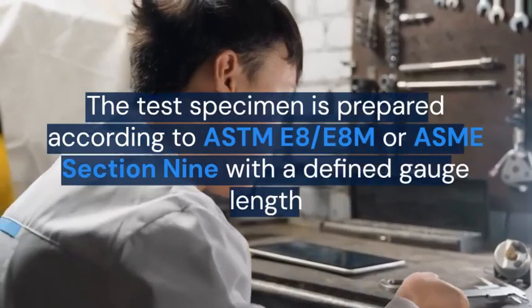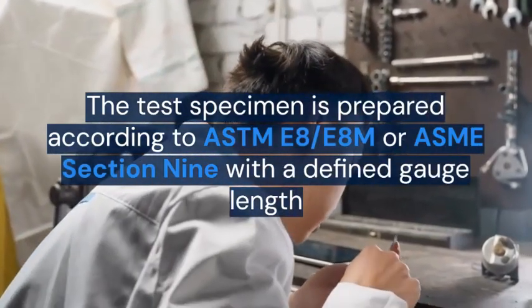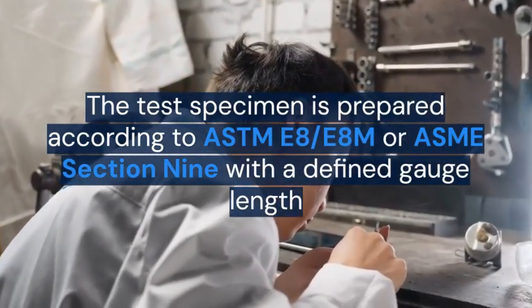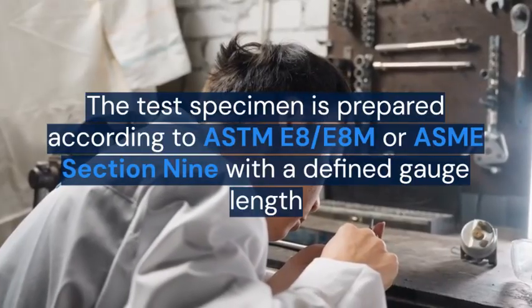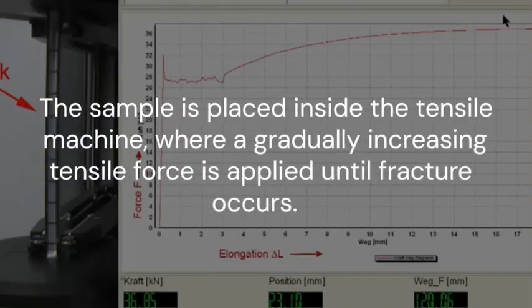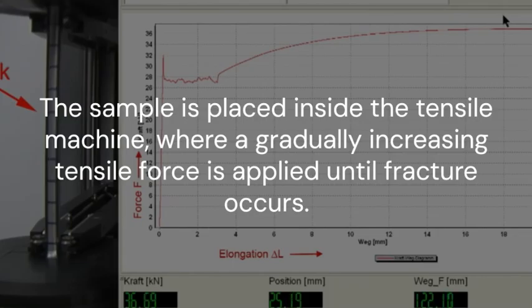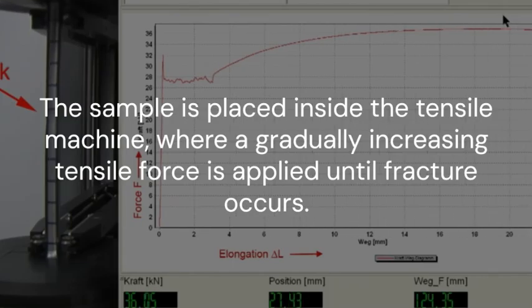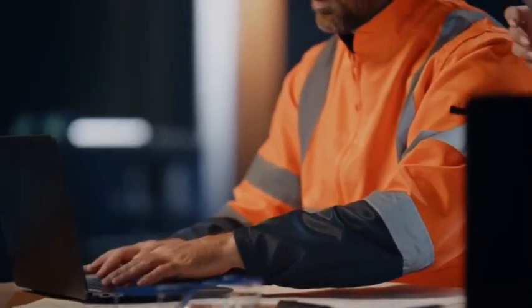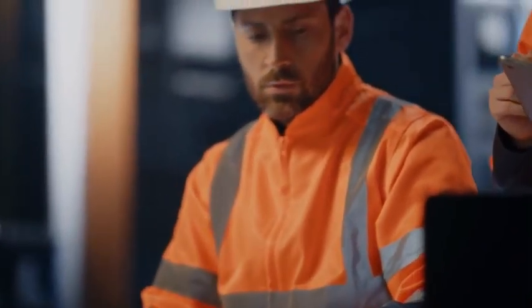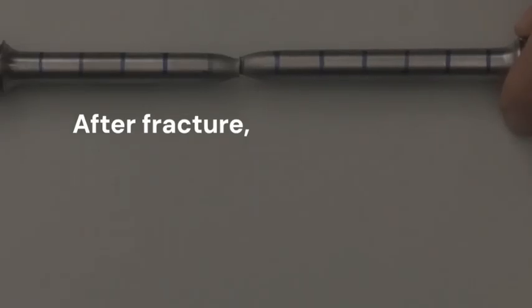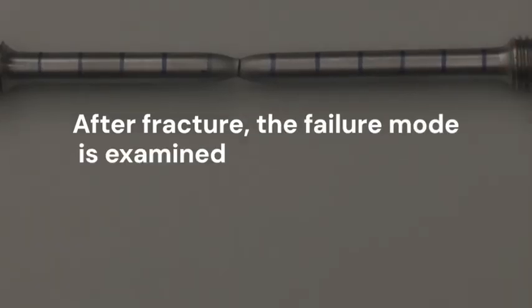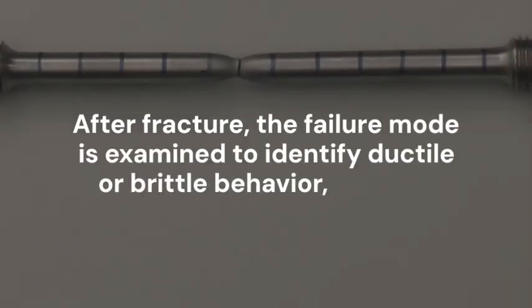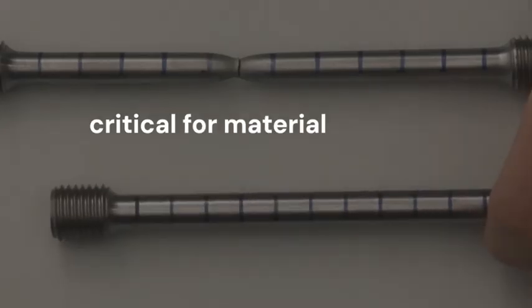The test specimen is prepared according to ASTM E8/E8M, or ASME Section IX, with a defined gauge length. The sample is placed inside the tensile machine, where a gradually increasing tensile force is applied until fracture occurs. During the test, the complete stress-strain curve is recorded. After fracture, the failure mode is examined to identify ductile or brittle behavior, which is critical for material and weld quality evaluation.